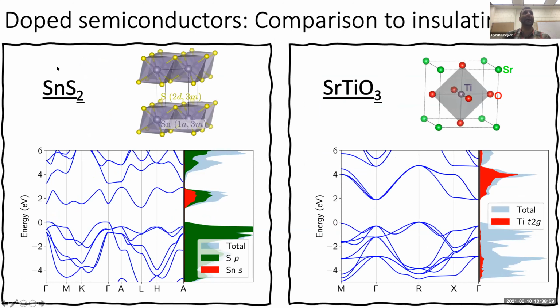We now turn to some more complicated systems that have optical phonon modes, so maybe the physics is more interesting or important. We take two systems. The first one is tin sulfide. It's a 2D layered compound. The structure is here. If we look at the electronic structure, it has a gap, so it's an insulator, and it has a very simple conduction band. It's just this single band that's a hybridization of sulfur P and tin S. And so to dope this material, we will be adding electrons into this conduction band.